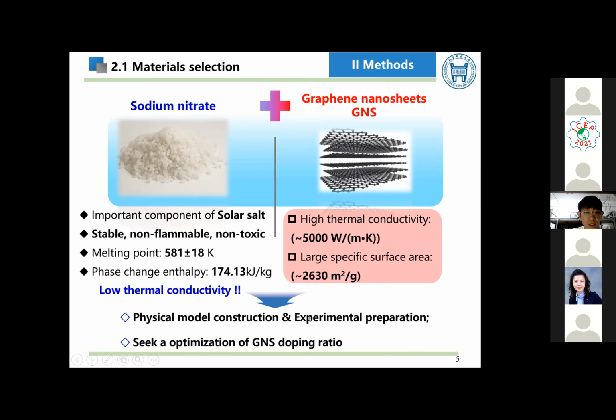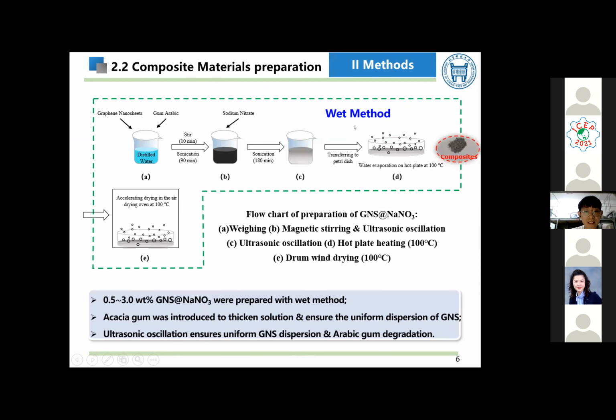The phase change characteristics and the thermal conductivity of the composite was tested experimentally, and the mechanism was further discussed by molecular dynamics simulation. The wet method preparation process of the composite materials was selected as shown in the figure. Samples of 0.5 to 3% doping ratio were prepared in order to explore the influence of the GNS doping ratio on the phase change thermal characteristics.